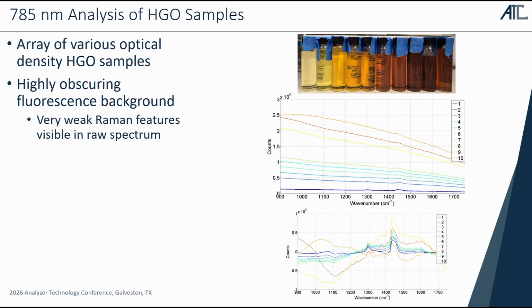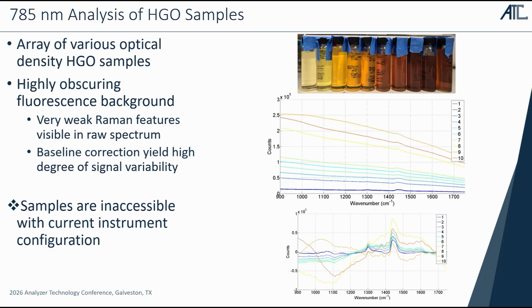And then even upon background subtraction and baseline, you can still see that most of our peaks are invisible, and that essentially these samples are just inaccessible with the current configuration. And so without a workaround to this, you probably would just have to give up on these samples in terms of wanting to quantify them.